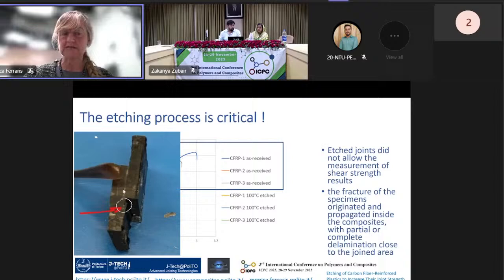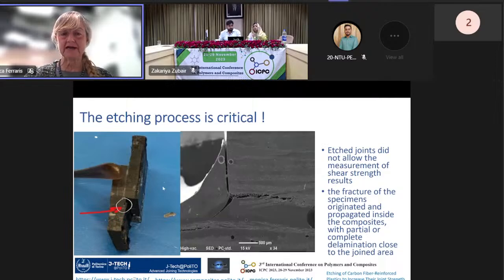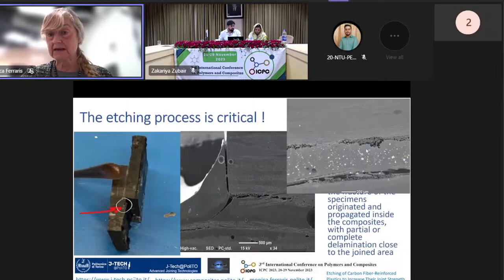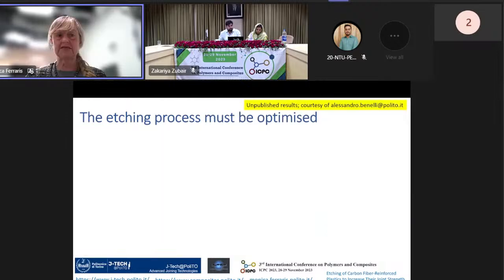You can see the jointed region here — the composite is affected, so you have a crack, and with higher magnification you see the joint is good and sound, but there's delamination because the etching is too strong. The joint itself looks perfect, but then you have delamination, so the joining material actually separates the two samples. This shows the etching process must be optimized.